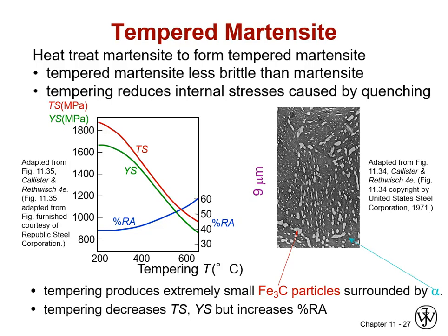So somewhere in the middle part of the diagram, before the lines cross, we probably want to stop. Again, balancing those properties the same way we did with recrystallization and strain recovery for cold work. At some point we're going to choose our tempering temperature and time and decide how much of the carbon we want to take out of that body center tetragonal strained lattice, and how much fracture toughness we need to recover and how much strength we're willing to lose.